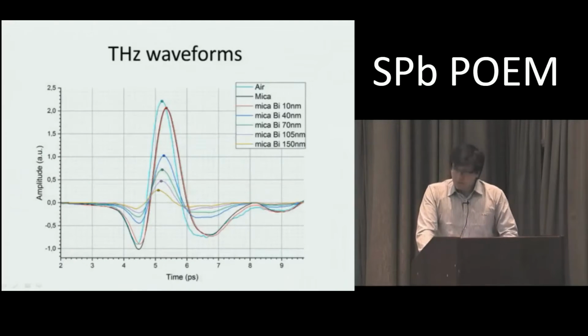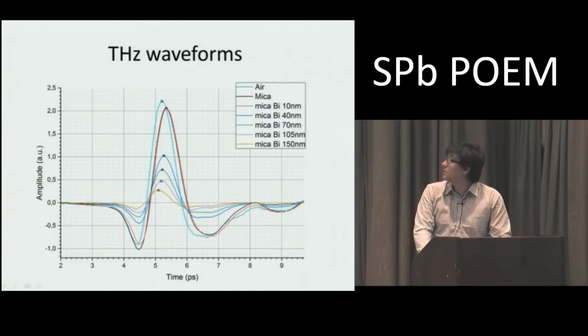In this slide we show the Terahertz waveform transmitted through the material, and we show that the high peak shifts to the left in time. We show that the pulse with increasing nanolayer of bismuth makes a very strong left shift.